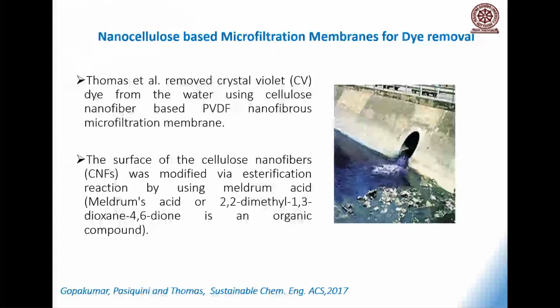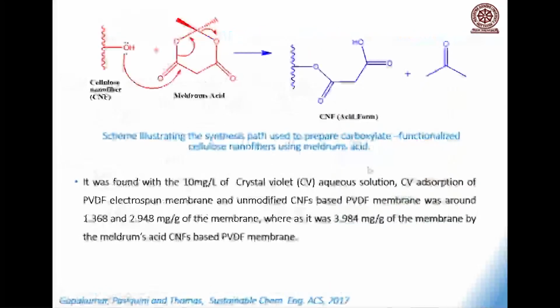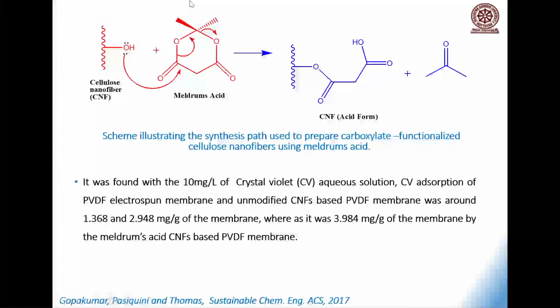I will show you a couple of our works. The first work we have done with Gopakumar, he is right now a postdoc. What we did is, we decided to remove crystal violet dye. From a company, you can see a textile company pumping out water. The water color is violet because of crystal violet. So what we did is, we did a small chemistry on the surface of nanocellulose. We made nanocellulose from banana stem, and we reacted nanocellulose with Meldrum's acid, a very simple reaction, and introduced COO minus group on the surface of nanocellulose. Very simple reaction we performed in the laboratory.